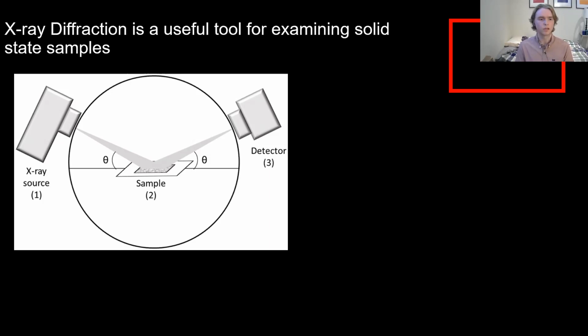And on a pretty simple level, the way X-ray diffraction works is you have your X-ray source, you have your sample, and you have your detector. And notice that we are beaming X-rays from the source off of the plane of the sample into the detector. And notice that there's an angle of theta made between the source and the sample plane, as well as the detector and the sample plane. Now, this is important to note because when I actually show you XRD spectra, we're going to be looking at an x-axis of 2 theta. And the reason our x-axis is in 2 theta is because of the symmetry between the theta angles you see here. So as the X-ray source is increased in its theta value, the detector is also going to equally increase in theta value. So that's why we're going to end up with that axis condition.